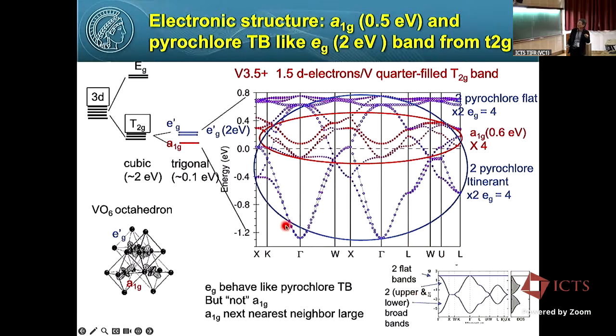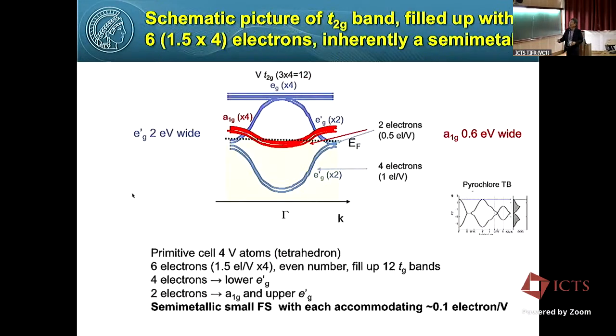Perhaps A1G pointing towards the center of the tetrahedron overlaps much less with the neighbors, and higher order hopping plays a very important role for A1G. But anyway, you can see some local character of the A1G derived band, plus the broad pyrochlore EG band. And so this is the band picture I showed.